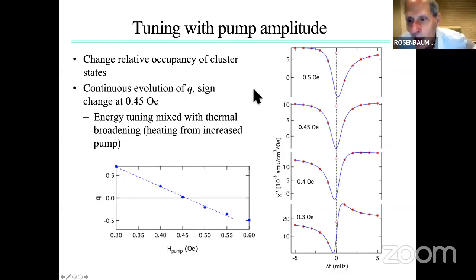Okay, let me note that you can also tune with pump amplitude. The pump amplitude, of course, drives the system harder, will flip some spins. We see here also that Q crosses through 0. This is the Fano Q as a function of pump amplitude, from 0.3 of a Gauss up to roughly 0.6 of a Gauss. Here the line shapes, but note that this is not as clean an experiment. There's probably interesting physics in this, but it's harder to deconvolute effects, because see how reasonably narrow at 0.3 of a Gauss this response is, and by 0.5 of a Gauss, you've already broadened this out.